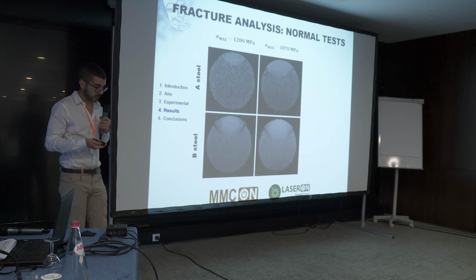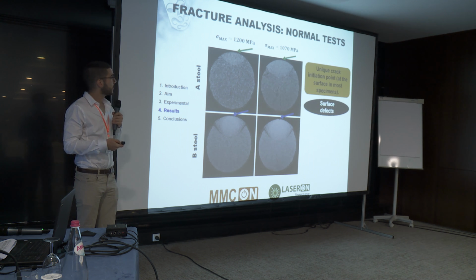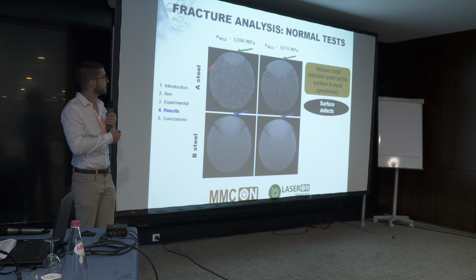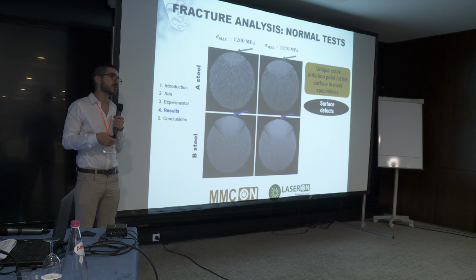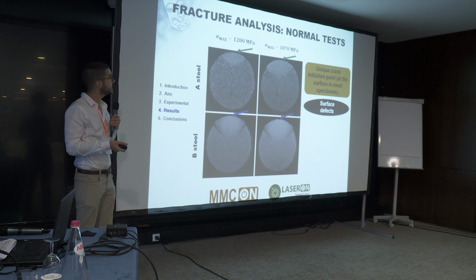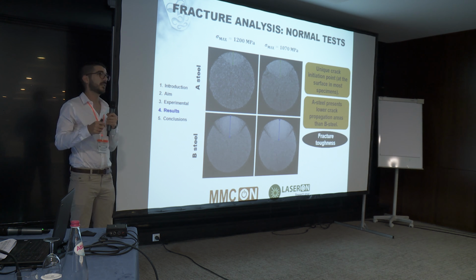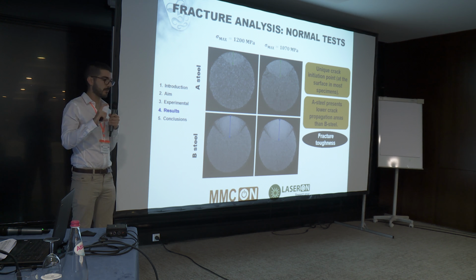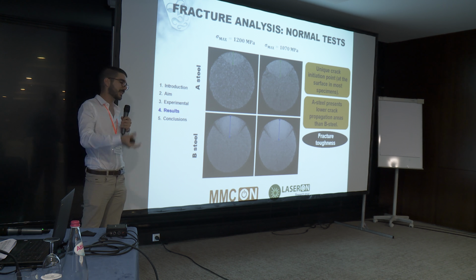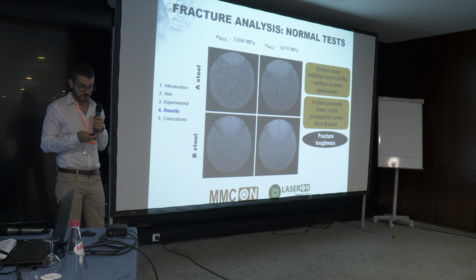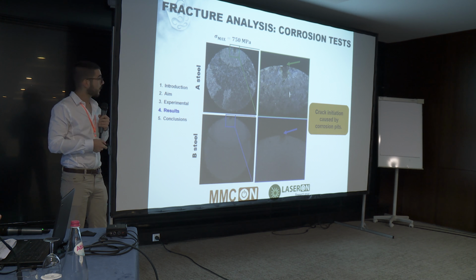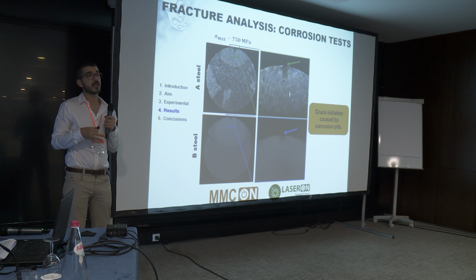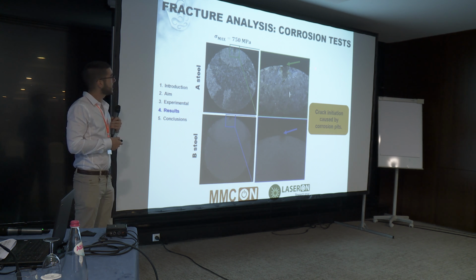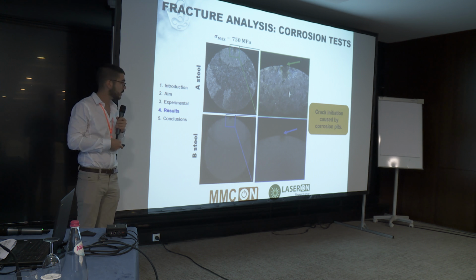And then we did some fracture analysis, where here I'm comparing both materials under the same maximum stress. We saw that in most specimens surface crack initiation took place, and also that B steel presented in all tests a much higher crack propagation extension than A steel, which may suggest that it has higher fracture toughness. In regards to the corrosion fatigue tests, we observe kind of the same features, but here it's clear that the surface crack initiation took place due to the formation of corrosion pits.